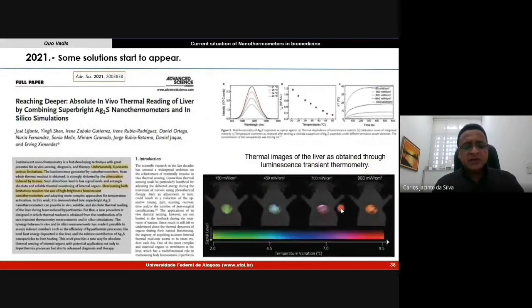In this most recent work, the authors demonstrated that the thermal readout is strongly distorted by the attenuation induced by tissue. This is solved by using the high-brightness luminescence nanothermometer, silver sulfide superdots, in combination with simulation. Thermal images of the liver were obtained through luminescence transient thermometry.